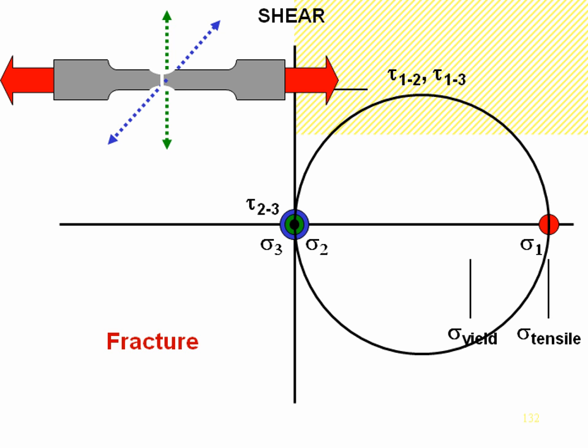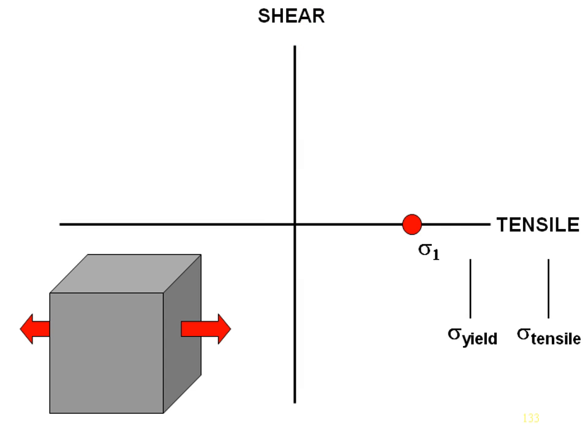Now we're going to complicate this a little bit. I'm going to add in a second stress field. So here's our cube that we looked at before. Sigma 1 is the same stress field we looked at before, but now I'm going to add in a second stress field, sigma 2, and I'm going to make it compression. Now, if it's compression, it's a negative value, so it shows up on the left-hand side of our chart. And we'll still have a sigma 3, but we're still going to make it 0.